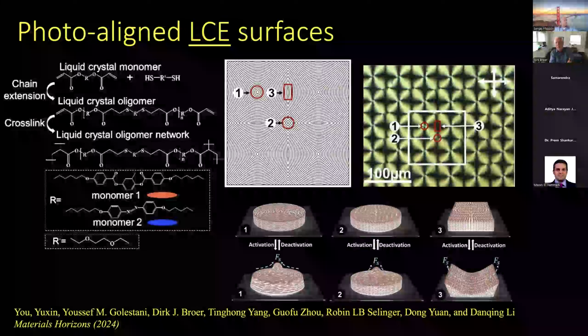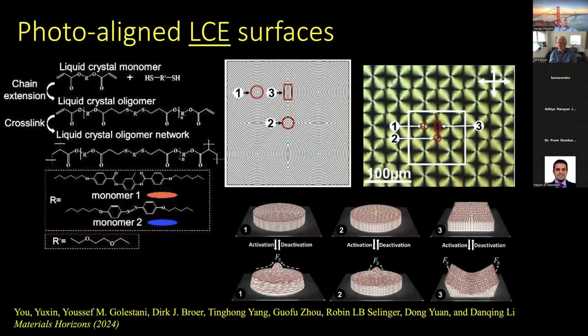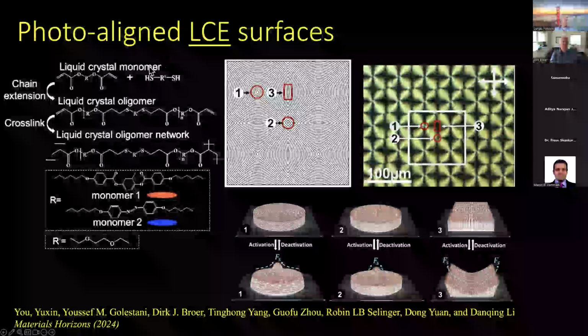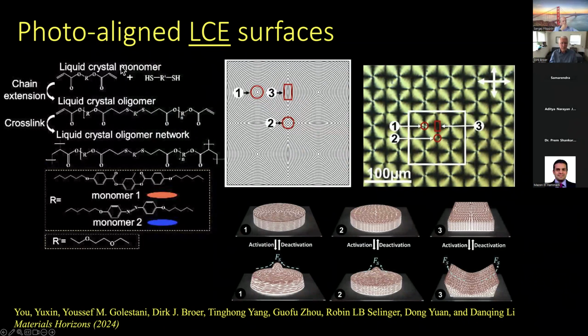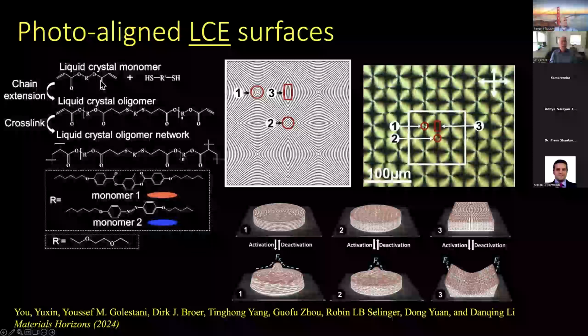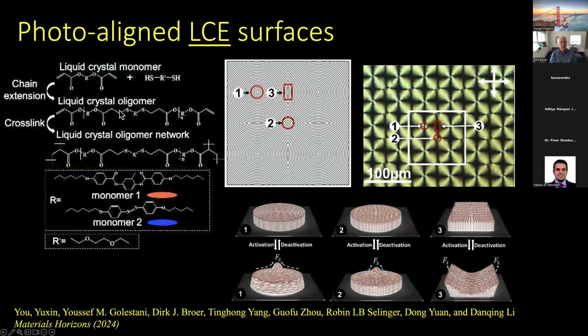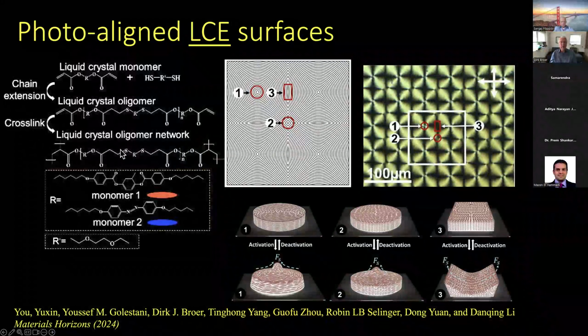Make a small step now to other surface structures. For this reason, we are using not our pure monomer system, but we go to the so-called liquid crystal elastomer surfaces developed by a number of groups in the past. Where you have a reaction between the liquid crystal monomer and a thiol to form an oligomer, and the orientation then takes place in the oligomeric state, and then the photo cross-linking takes place to freeze that orientation in. And the advantage of this system is that you increase even more the robustness of the systems, but also the mobility. You are basically bringing the glass transition to lower values.